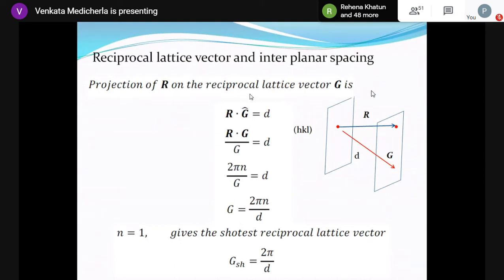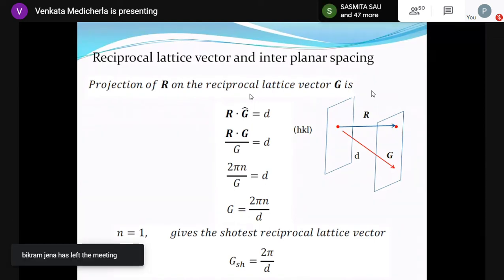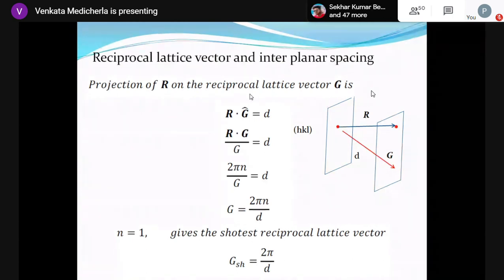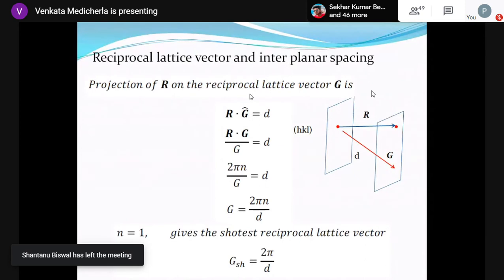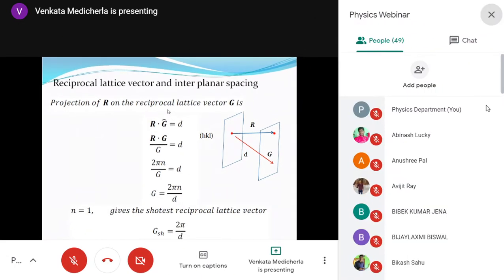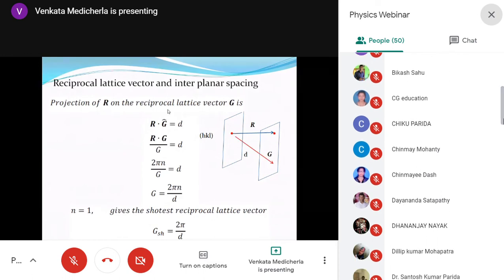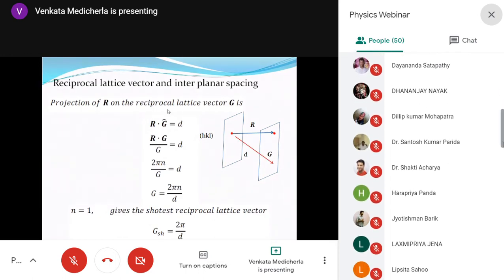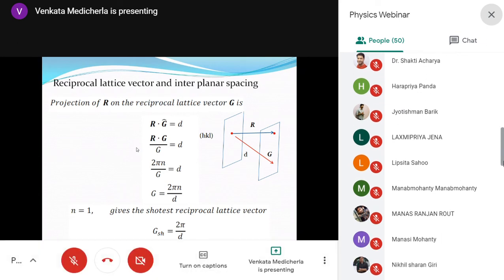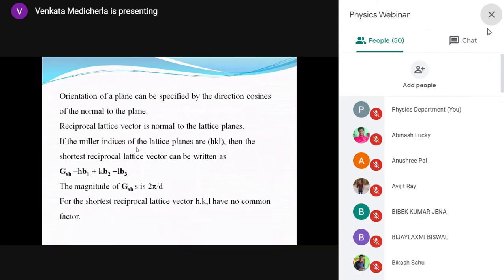So d equals 2π/g_shortest. If you can find the shortest reciprocal lattice vector, you can immediately find the interplanar spacing d. In some cases — like cubic or orthorhombic systems where axes are orthogonal — finding d in real space is manageable, but if the axes are not orthogonal it is very difficult. In that case, use the reciprocal lattice: just compute 2π/|g|, and that gives you d_hkl.